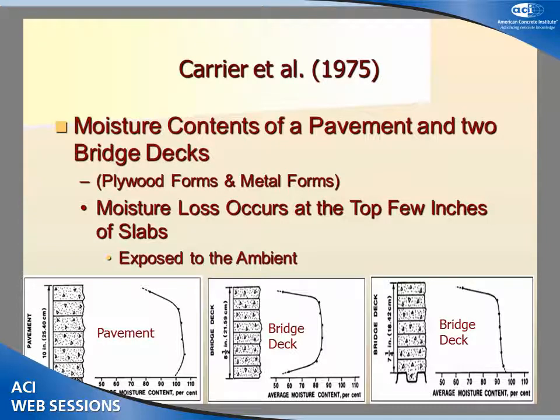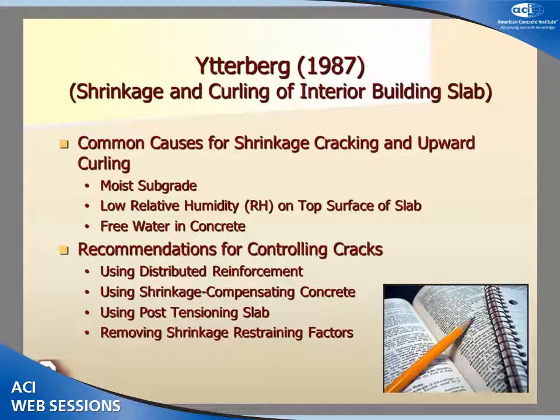On your left is pavement, which has just the top surface exposed to the ambient. The second one is bridges, which have both top surface and bottom surface exposed to the ambient, and the last one is the bridge deck, which was formed on metal forms and only the top surface exposed to the ambient. So he concluded, or he showed based on his graphs, that moisture loss occurs at the top few inches of the concrete, which is exposed to the ambient.